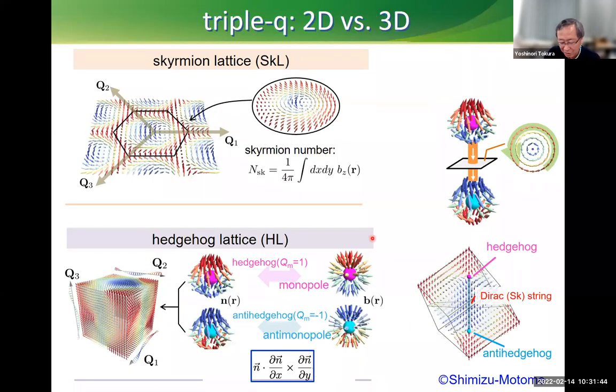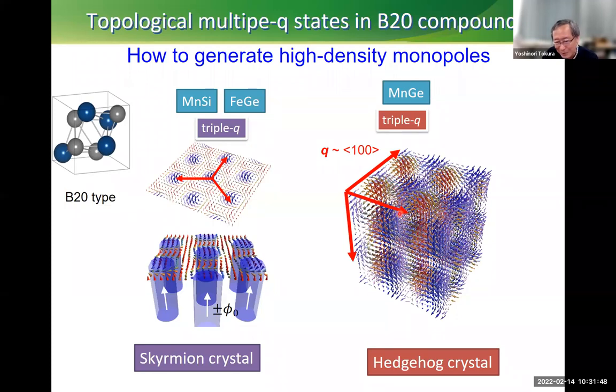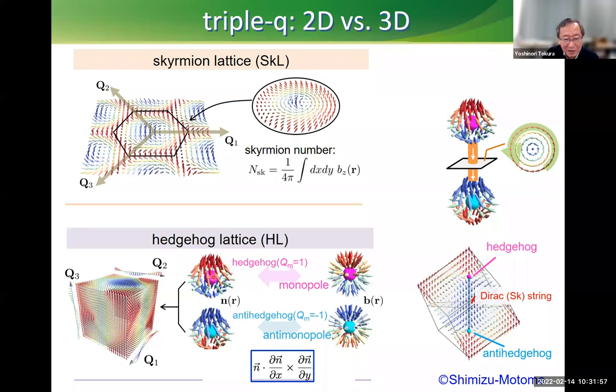This three-dimensional structure shows very complicated structures. But if you scrutinize every singular point, it's composed of this hedgehog and anti-hedgehog dislocation singular point. Of course, a hedgehog is converted to the monopole in terms of the emergent magnetic fields. Anti-hedgehog is likewise an anti-monopole. So in the compound, there is certainly the hedgehog, anti-hedgehog point, or monopole, anti-monopole point. But in between these, we see the skyrmion string bridging over the monopole and anti-monopole. This is a very close analogy to the case of the Dirac string and the monopole, anti-monopole that are directly connected, bridged by the Dirac string. In this case, the Dirac string is nothing but the skyrmion string.